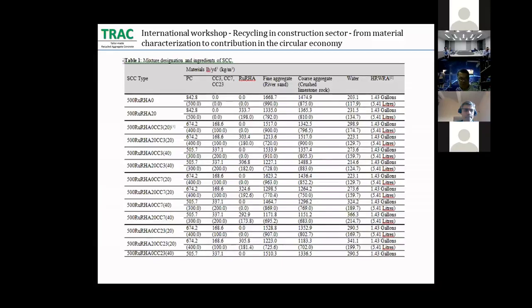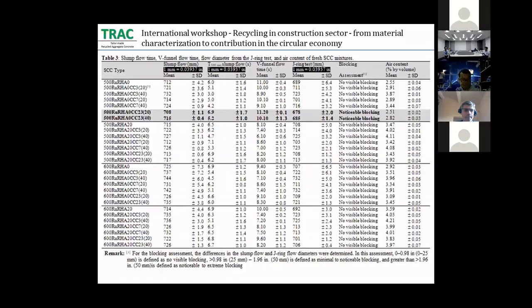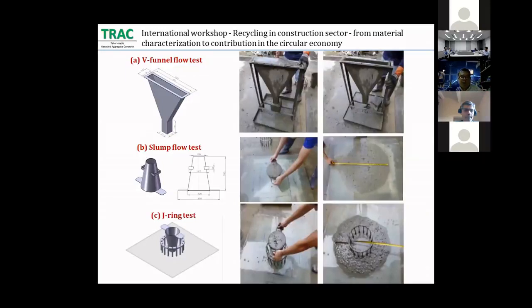CC was used both as a cement replacement material and as a filler, and the workability, compressive strength, and resistance to sulfuric acid of the self-compacting concrete were tested. The workability parameters of self-compacting concrete containing rice husk ash and calcium carbonate include initial slump flow, T500 time, V-funnel flow time, and J-ring flow. The blocking depth of self-compacting concrete was assessed by calculating the difference in diameter between the slump flow and J-ring flow. Based on the practical flow criterion of every self-compacting concrete mixture in this research, the initial slump flow is 725 millimeters diameter. Workability can be categorized into two main capacities as follows: filling ability and passing ability.